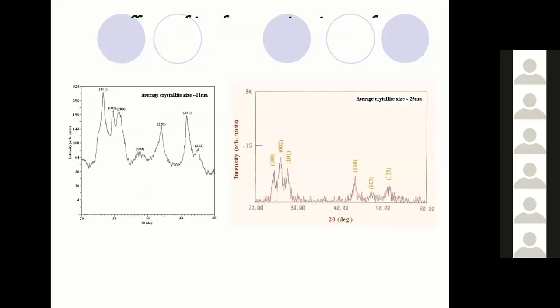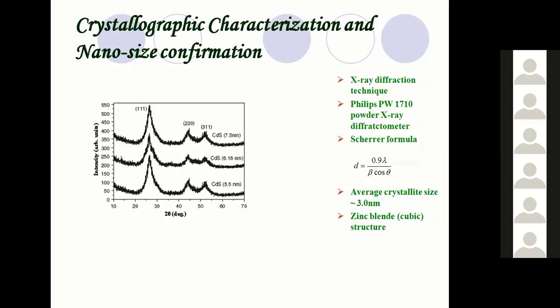Similarly, it is the beauty of the nanomaterials that the crystal structure will also change. In case of the cadmium sulfide, when the particle size was approximately 25 nanometer, the crystal structure was wurtzite, hexagonal. But when the size was reduced to 11 nanometer, it had a mixture of the cubic zinc blende as well as the wurtzite, hexagonal structure. But when we reduced the particle size further, it became zinc blende.